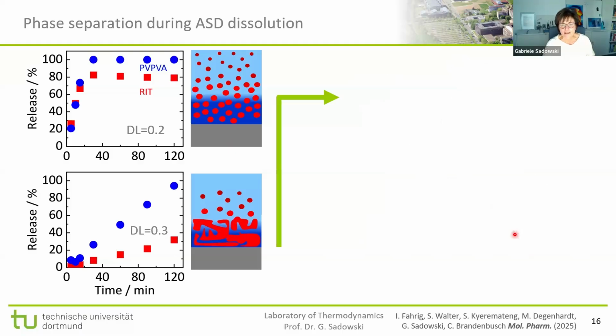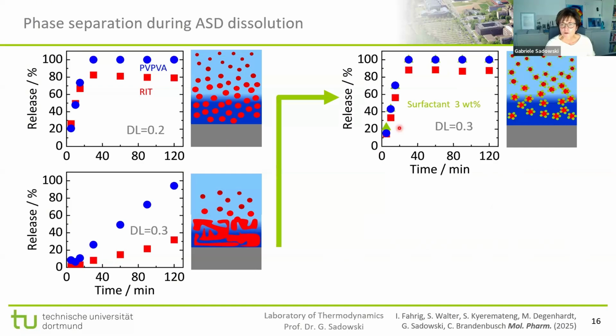So now the idea of adding surfactant. The drug load is the same, but now we have a third component in the ASD, which is a surfactant, up to 3 weight%. And this indeed really improves the dissolution behavior. We have a similar picture to the one at 0.2 and no surfactant. So we could get back to the nice case, so to say, by adding a surfactant and keeping the high drug load. 0.3 is a higher drug load, and this is more or less totally released.